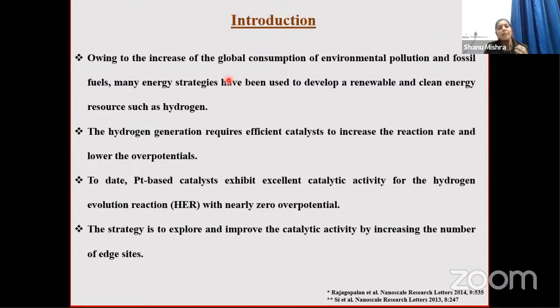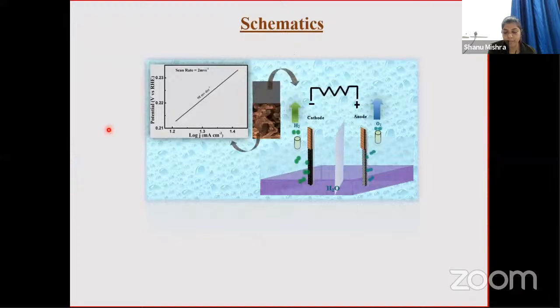But the thing is that platinum is very earth scarce, and its skyrocketing price is hindering its use for commercial application. So there is a quest to find an earth abundant, inexpensive material with improved catalytic performance. For this purpose, we have synthesized iron nanoparticles by two different routes, the green route and the chemical route, and used these iron nanoparticles for synthesis of MWCNT. With this MWCNT, we are showing the hydrogen evolution reaction, and we also use it in an indigenously designed electrochemical cell for hydrogen production and collection.